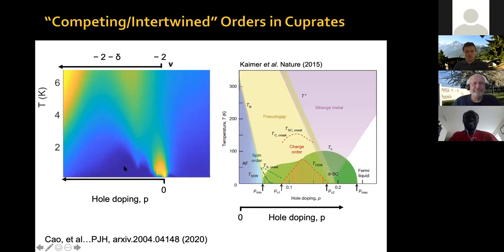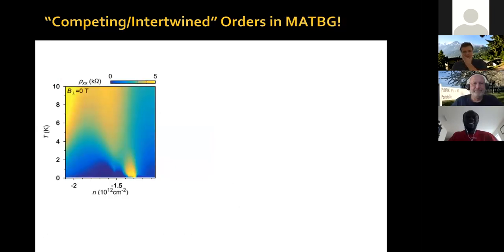So this is actually a theoretical phase diagram, but we're measuring this continuously. This is actual data. You can see the shape of the superconducting dome with a depletion in that region. So now, when we look at this, we were like, what is that thing? It seems like there is something here that wants to compete with superconductivity and creates a depletion there. Why don't we suppress superconductivity, for example, by applying a small perpendicular magnetic field, and let's see what's really underneath there. So we did that.